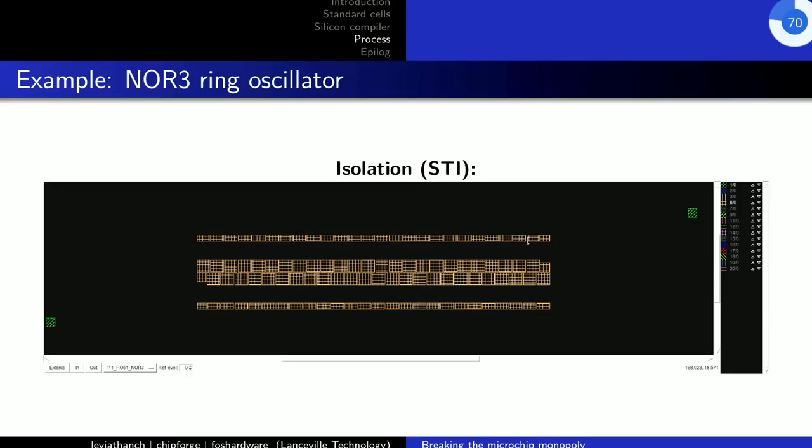It's really simple. After you get your wells out of the furnace, so I did a little detour, you want to make sure that the lateral diodes, which came into existence after diffusion, don't create unwanted short circuits. So we use a technology actually developed much later, after one micron had already been out. It's called STI, shallow trench isolation. It's from the ULSI technology, as well as the silicide we use to reduce the resistance of the polysilicon gates.